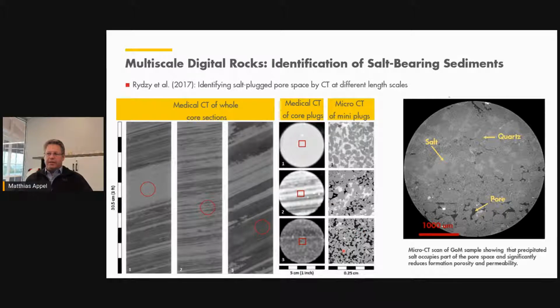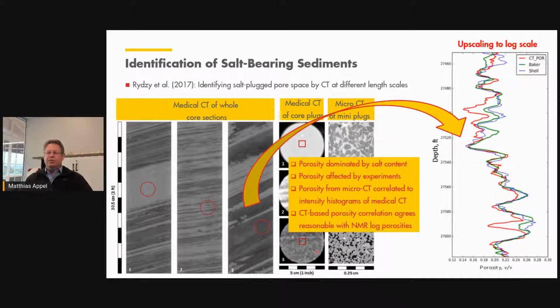of salt. And that helps then to create a correlation between the attenuation coefficients from the medical CT imaging and the porosity information that is derived from the high resolution mini plugs that have been scanned on the micro CT scanner. And with that correlation in mind, one can get an information of porosity directly from the medical CT scan, well, and then upscale that to the log and compare to a variety of other logs, like 2 different NMR acquisitions here. And the correlation is not bad.